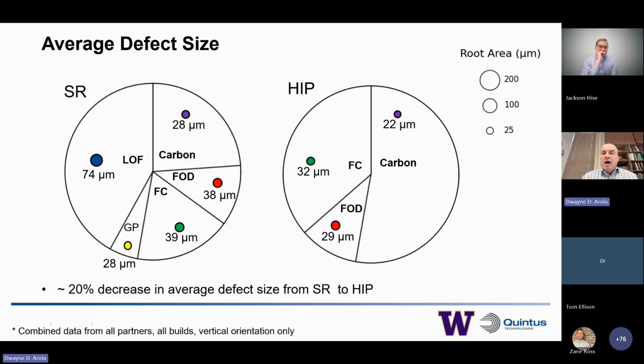And now if I look on the right, the same pie chart distribution for the HIP condition, you see again the lack of fusion and the pores are gone. No contribution in that space. You see also then our three remaining categories: foreign contaminants, foreign object debris, and carbon.